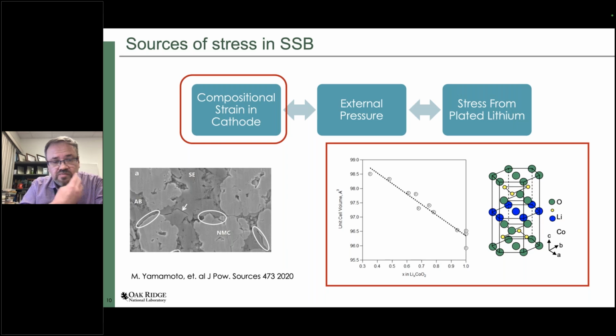And when you do that in contact with the solid electrolyte, which is typically ceramic, that leads to the formation of cracks, either at the interface or in the bulk of the electrolyte, as shown in this SEM image. So think about it as if you're making a composite material with particles and matrix having very, very different coefficients of thermal expansion, and then you try to warm it up. So the problem here, in addition to the volume mismatch, is that those strains are anisotropic. The expansion typically happens along the C-axis of the crystal, and they're highly inhomogeneous.